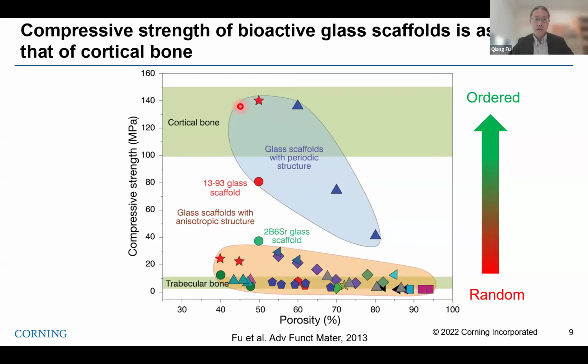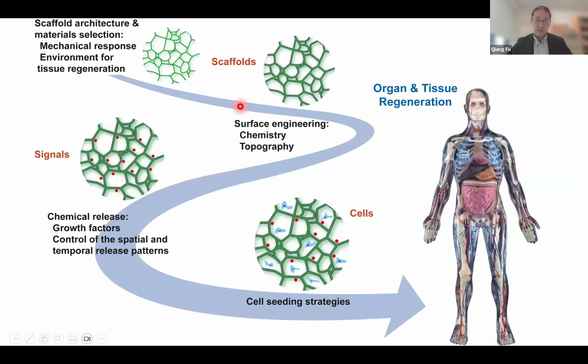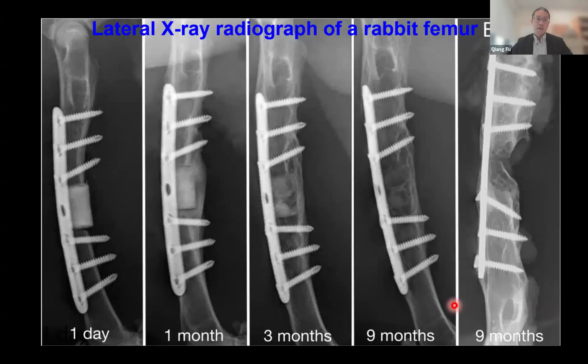We collaborated with our friends in the hospital. We actually loaded the scaffolds with cells and signals, and then implanted them in a large bone defect model. In this case, we created a segmental bone defect in a rabbit, and then put a cylinder-like 3D printed glass scaffold within this gap. This is after 1 day. You can see the clear gap between the bone defect and the glass scaffold.